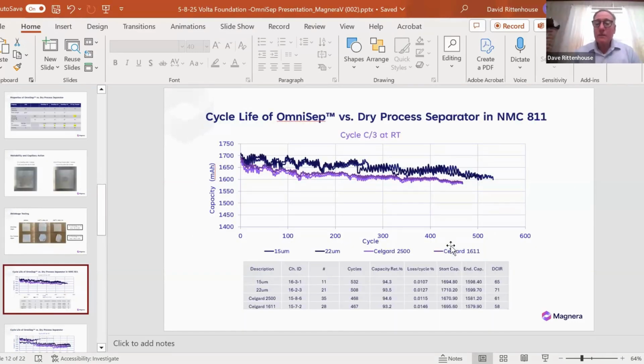Very important is the performance. We made our cells, of course, we had to plan our testing regimen several years ago. At that time, NMC 811 was the predominant chemistry, which is why we chose that. It's also less forgiving, as you know. So these top two lines, the 15 micron and 22 micron OmniSep, and these bottom two lines are 2500 and 1611. We chose those as the reference to compare the highest charge rate stretched film versus OmniSep, and we have the rate capacity retention shown here, 90 out to here 94%.